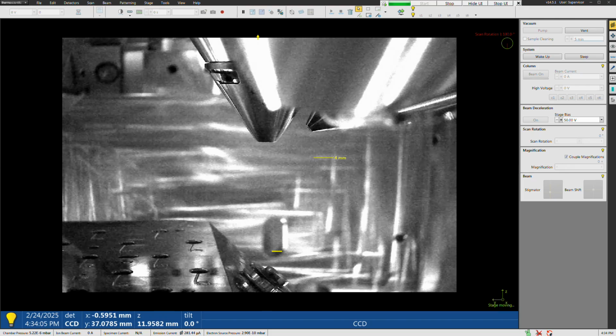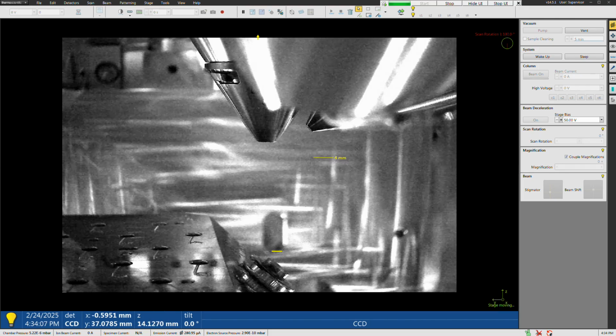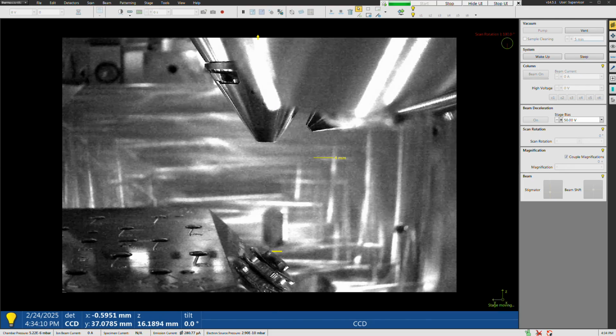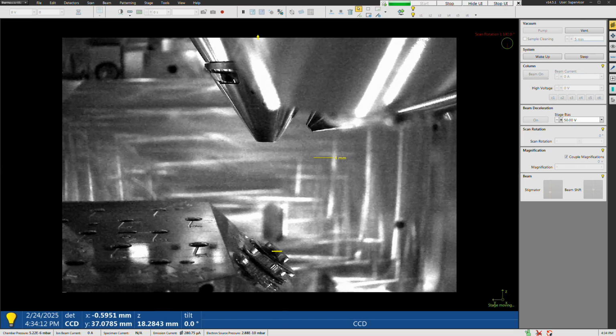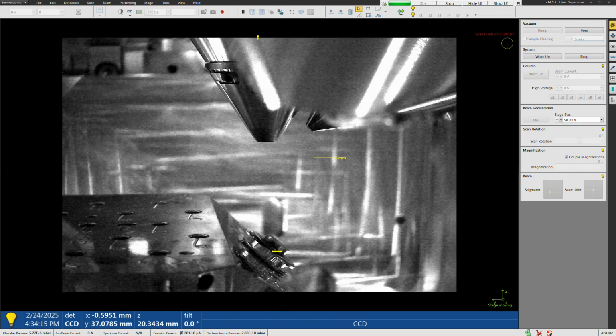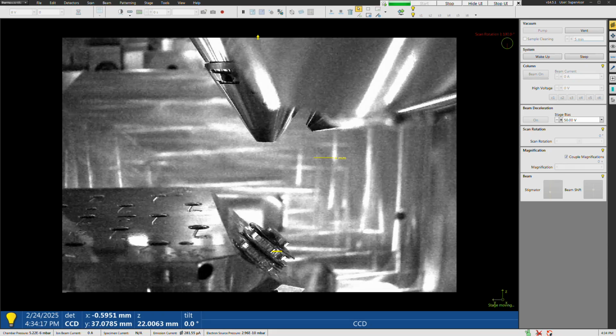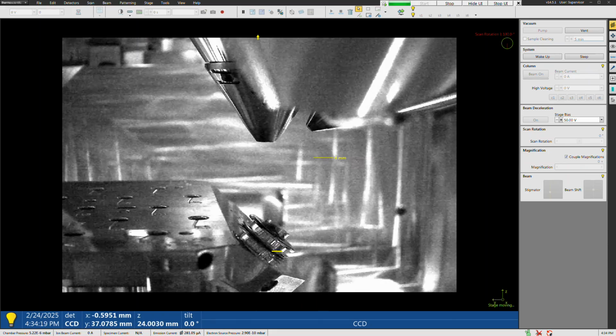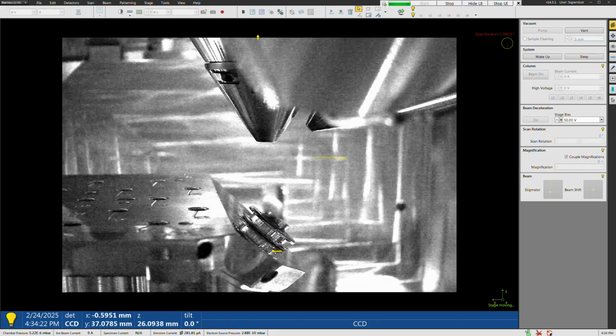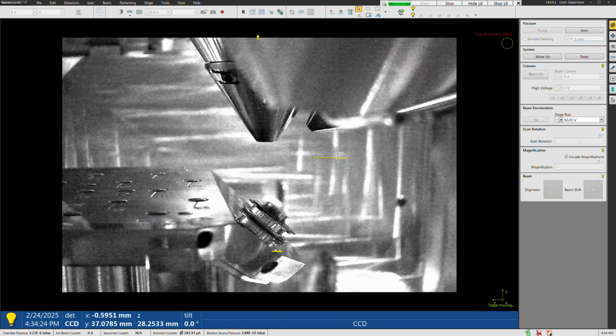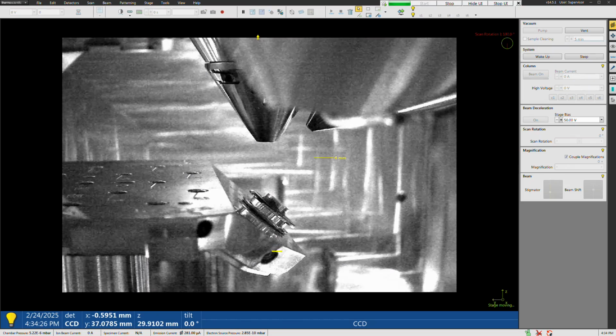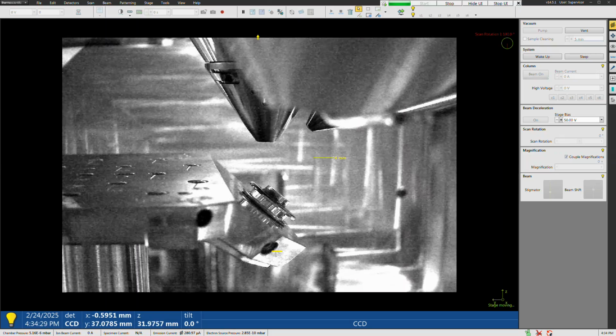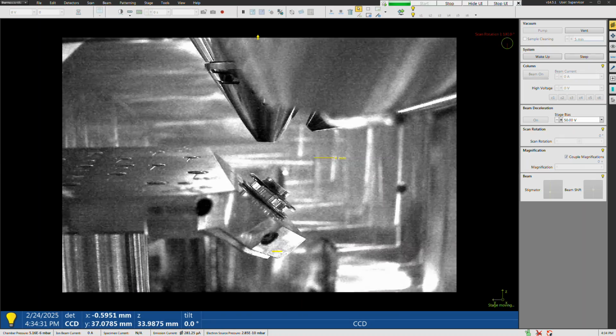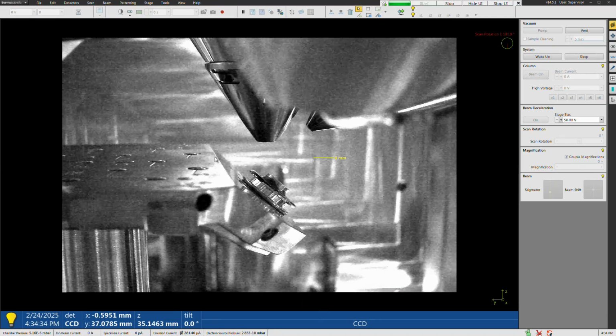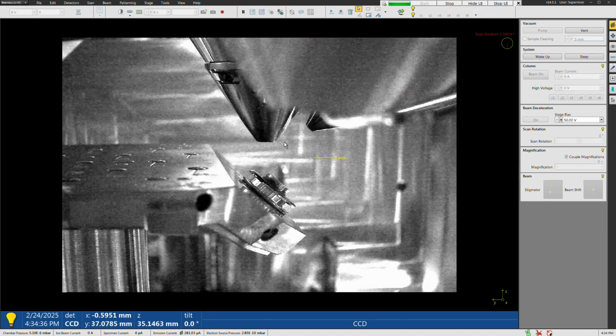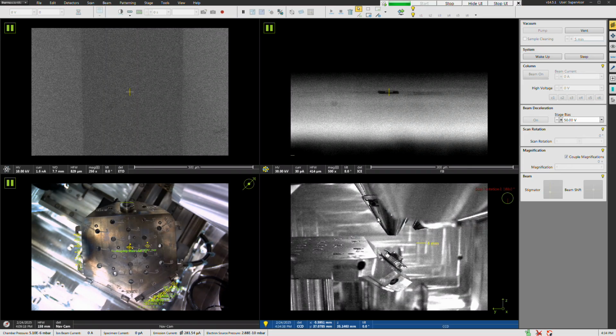So your eucentric working distance on the system is 4 millimeters. The optimal working distance for the EBSD camera is actually 8, although this system is calibrated to work, I believe, between 4 and 16 millimeters. But if you can do EBSD at 8 millimeters, that's what you want to do. Okay, so we're going to stop a little bit short. I want to keep this edge here below the pole piece, and I'm going to show you why in a second here.